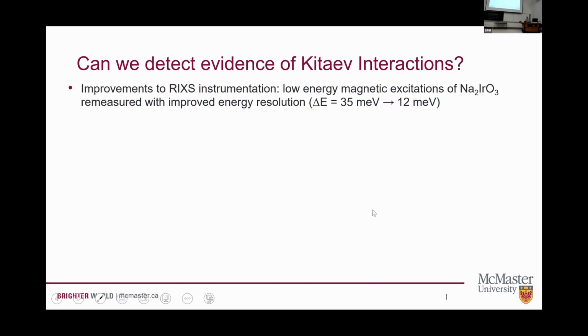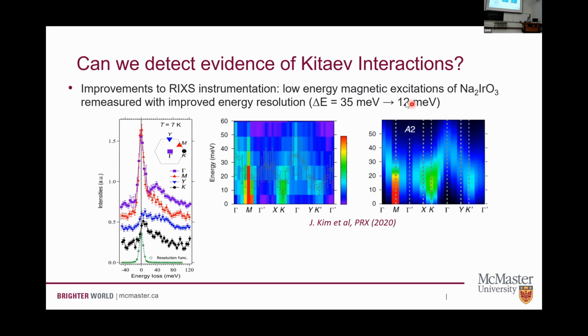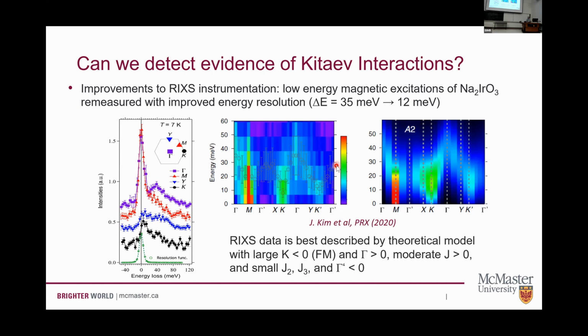So a few years later, the RIXS energy resolution has improved, can go back and measure this again. So at the time we were using sort of world leading resolution, which is about 35 meV. With new analyzers, you can get about a factor of 3 times better than before. And you can see that this feature really is real. It exists. The signals go way down once you start doing these high resolution measurements. But if you take the time, you can map them out.